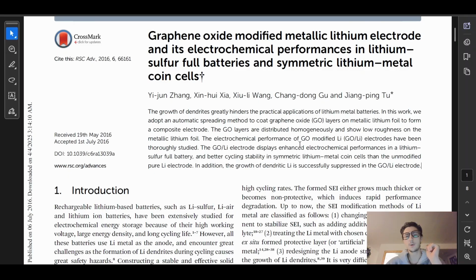foil. The electrochemical performance of the graphene oxide modified lithium GO/Li electrodes have been thoroughly studied. The graphene oxide lithium electrode displays enhanced electrochemical performances in a lithium sulfur full battery and better cycling stability in symmetric lithium metal coin cells than the unmodified pure lithium electrode. Interesting. In addition, the growth of the dendritic lithium is successfully suppressed in the GO/Li electrode. Damn! Alright.